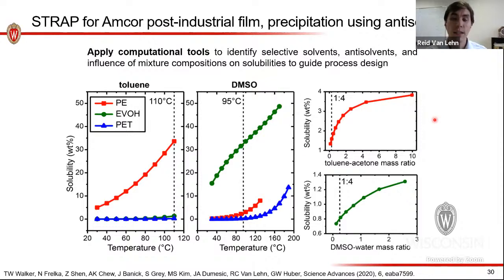So for example, we could identify that for a given film provided to us by Amcor, which is one of their highest volume films that is currently not recycled at all, we can apply our computational tools to identify solvents, anti-solvents, and temperatures at which the solubility of one component, for example, polyethylene, is very high, and the other 2 components, EVOH and PET, is very low. So if we go and put our film into this solvent at this temperature, about 100 degrees Celsius, I should only be dissolving the PE, which means that now I've selectively recovered that. I can add an anti-solvent to take it back out.